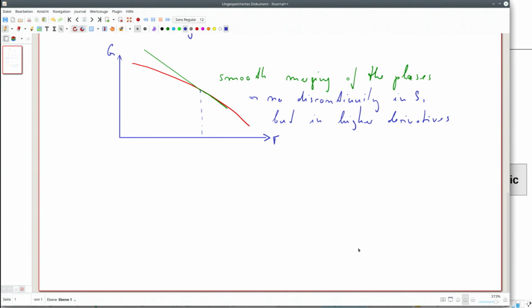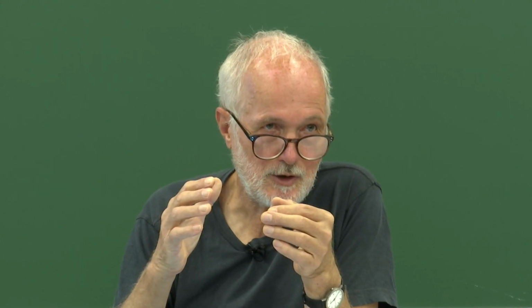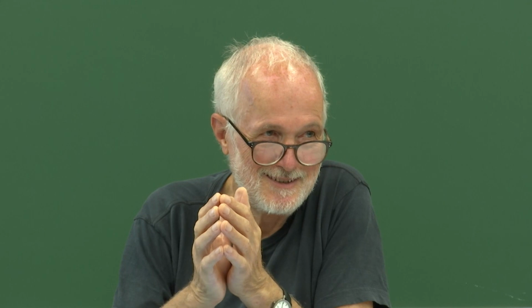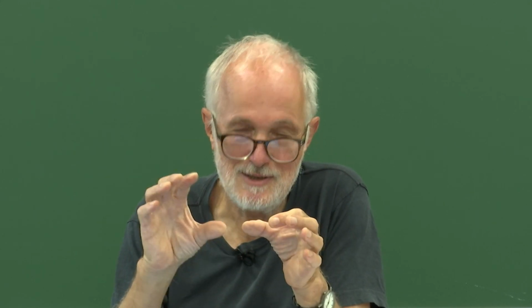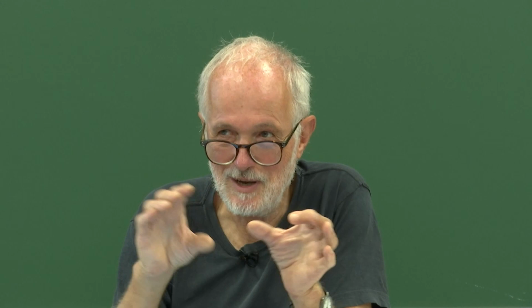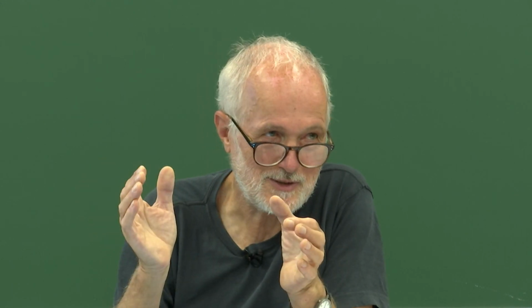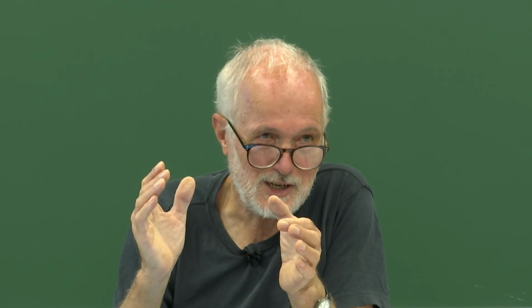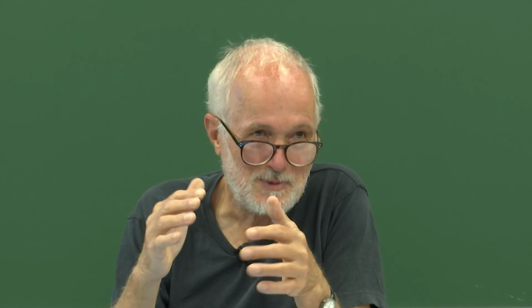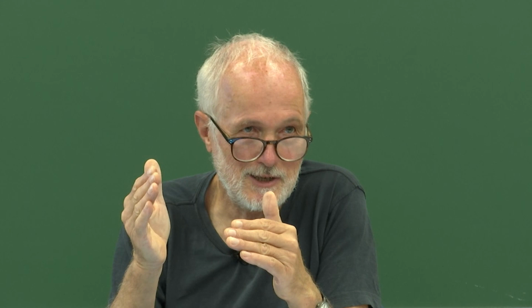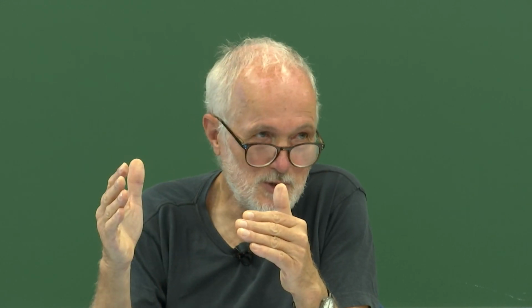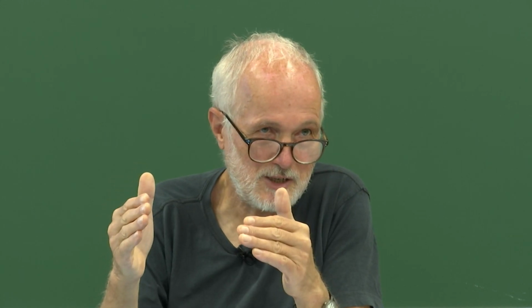I don't want to go too much in detail, but it's obvious that to have such a smooth transition from one structure, if we speak about a structural transformation, to another structure, there must be a continuous path. If you change the structure from FCC to BCC, there's nothing in between. You cannot go smoothly from FCC to BCC. So this must be a first order phase transition. For these ordering transformations, as I said, they are obtained by putting the majority on one sublattice and the minority on the other sublattice. And there you can smoothly approach zero. That's why we can have second order phase transformations there.